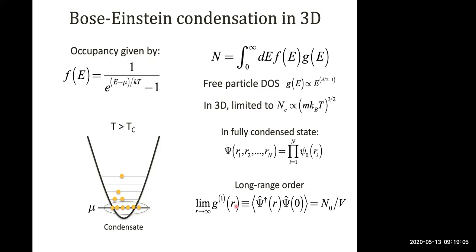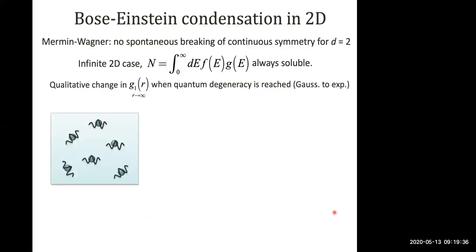order. So if you consider the spatial correlation function, which is basically telling you about the phase relation of the condensate at 2 points in space, even at very long distances, you have a non-vanishing value of this correlation function, and that value actually corresponds to the condensate density. So N0 corresponds to the number of particles that are in the condensed phase. And if you were to normalize this, actually it would be the fraction of condensed particles.